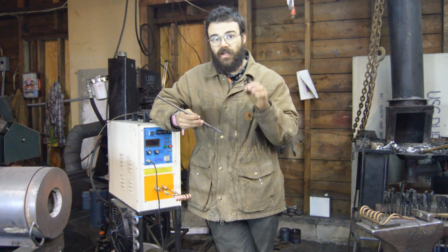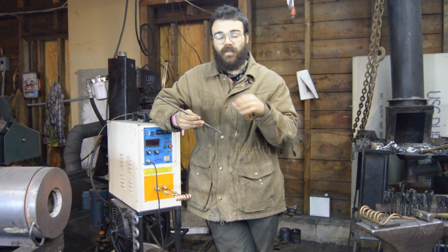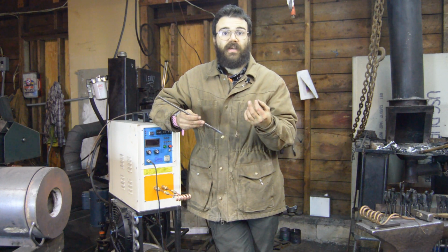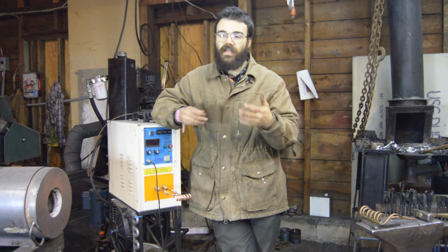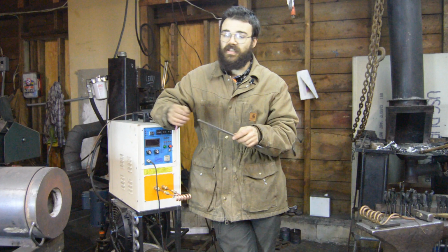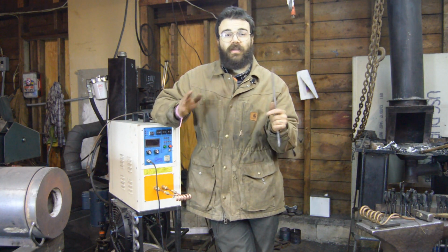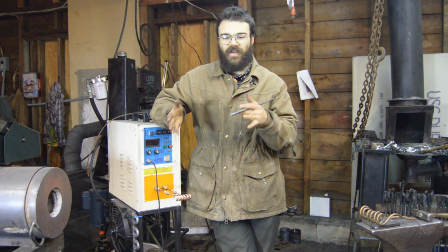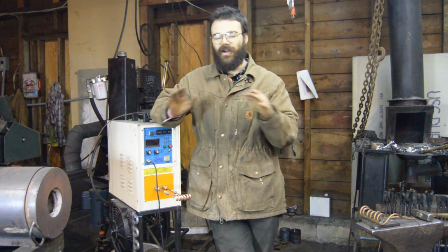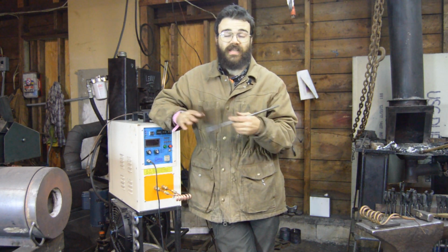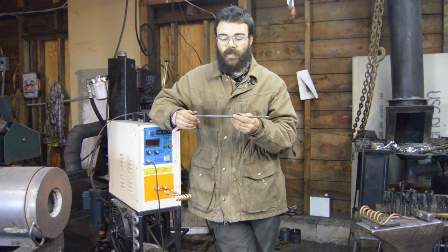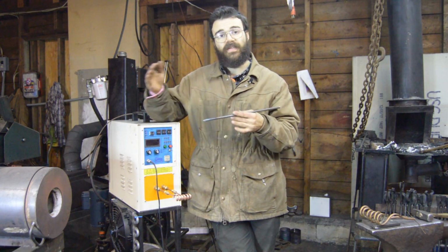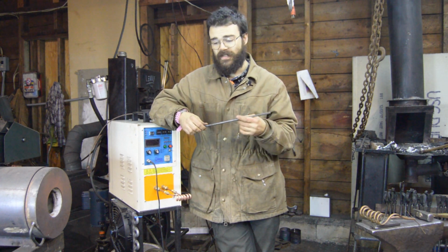However, when you hit the Curie temperature of the material, it loses its ability to become magnetized. So you'll notice this with steels. If you're into heat treating or anything like that, you heat up until it's not magnetic, and then you can quench. The Curie temperature and the transformation temperature for austenite are not necessarily related, but this is a common technique, and it shows that ferromagnetic materials heated past a certain point lose their ability to become magnetized.